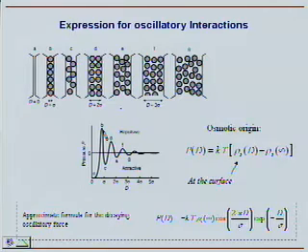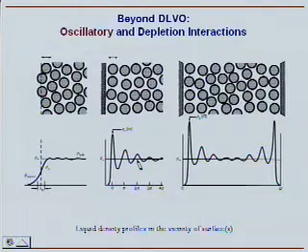If the particles fit well, then you have high osmotic pressure, which is repulsive. The surfaces are really repelled because you have lots of stuff between them. If you're further out, you don't have enough particles, you have lower osmotic pressure, which means attractive. And this is the origin of the so-called oscillatory forces, where eventually the forces go like that: attractive, repulsive, smaller attractive, smaller repulsive, even smaller attractive, even smaller repulsive, and so on. This even smaller comes from the fact that, if you remember, the further away the surfaces are, the less organized the system is in the middle.